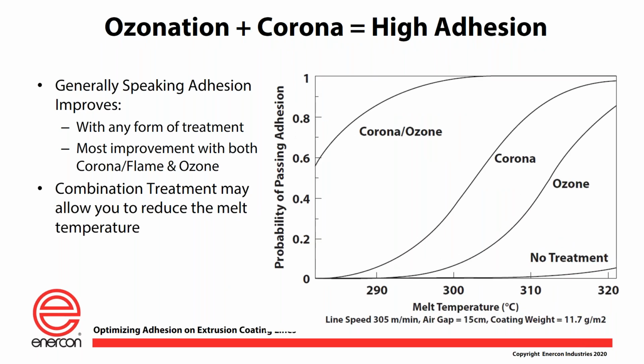Next slide. So yeah, again, here's a great example. Ozone Corona, it will improve your adhesion profile really without doubt, and it really can be improved even further as you add these other surface treatments in addition. And when you stack all this together, and then you take into account that you can run your lines faster, you can drop your die gap, you can then drop your temperature of your die. These are all very, very powerful tools that you have at your disposal now to really increase your productivity and provide your customer with a better product.